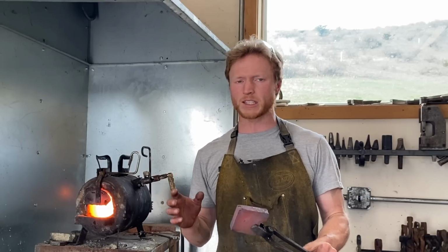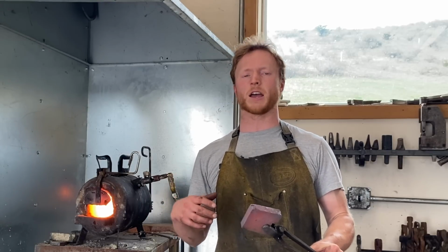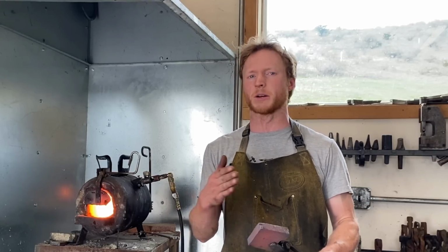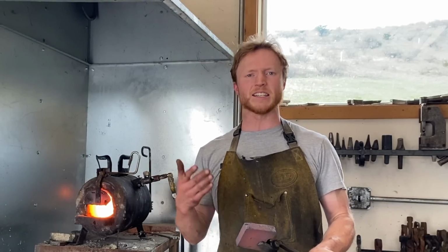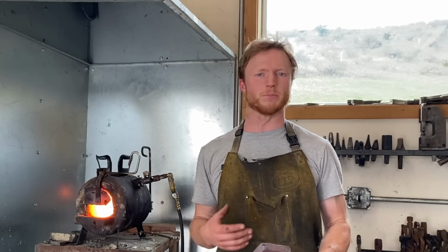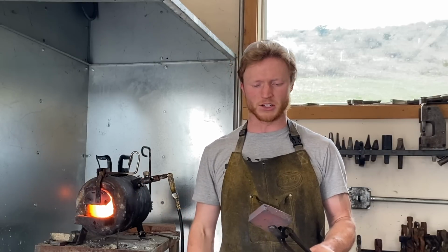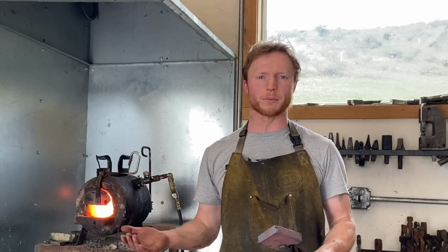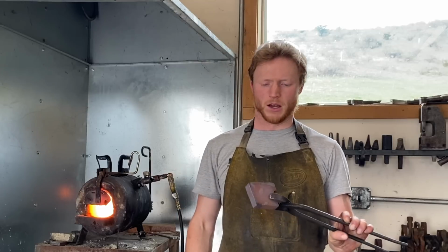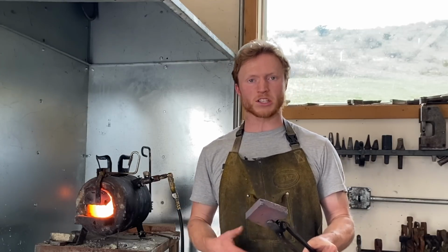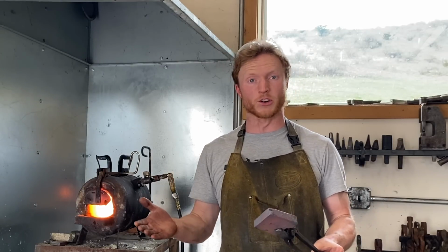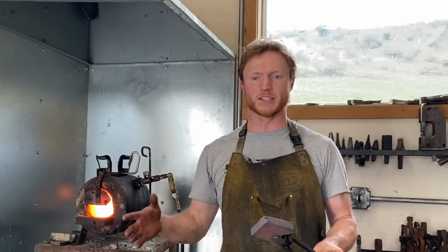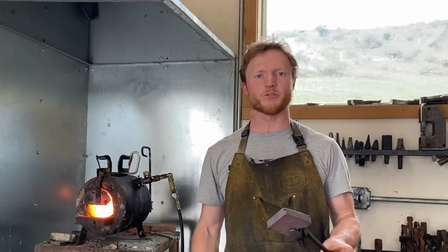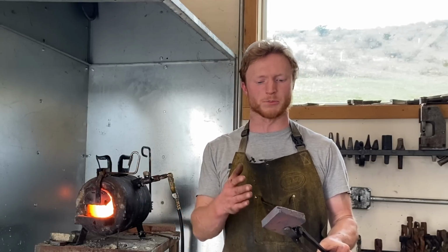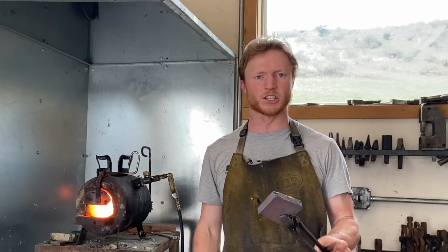But it's a little bit risky because if I forge really closely and don't have as much to grind, then I can get decarburization in the blade and have other issues like that. It's also more prone to warping in the heat treat. Anyway, it'll be a trade-off. We'll see if it works. If not, I'm going to have to start all the way over from the beginning because I didn't have enough damascus to do another bigger blade. This is the only chunk that I have.